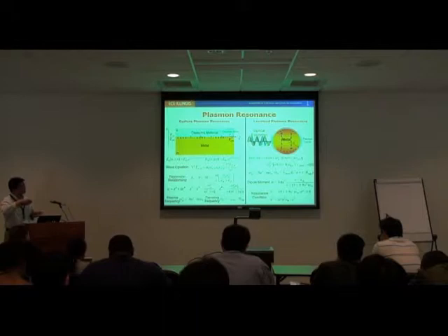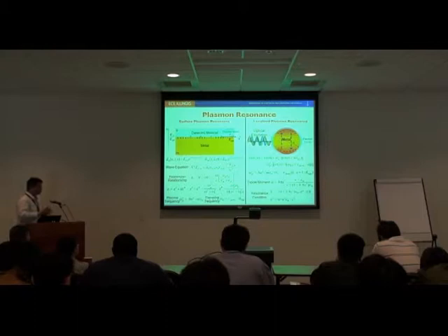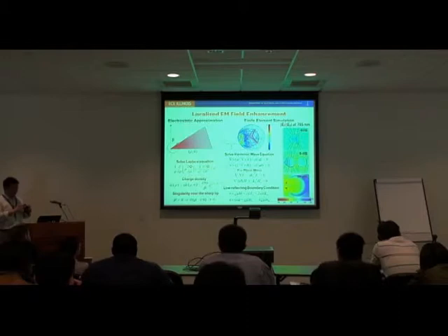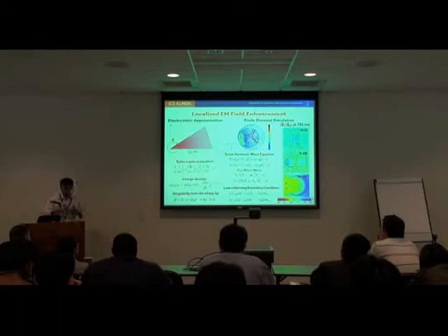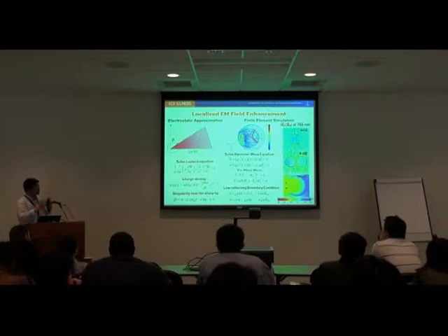If we can control the free electrons in the metallic nanostructures and make them start resonating, then we can accumulate those electrons at some sharp point. When that happens, you have a pretty high charge density at that local position, and then you can create a very high electromagnetic field at that particular point. Those points in the surface field are called hotspots.